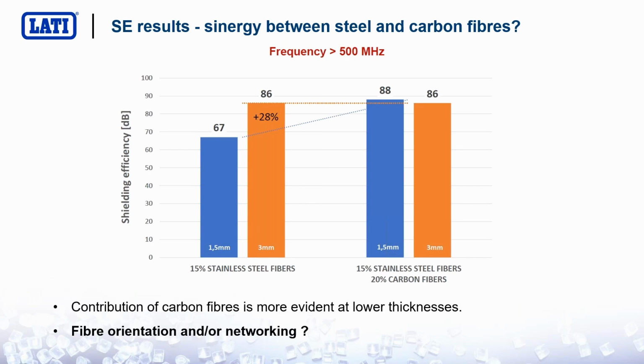We think that orientation improves networking, improves the number of contacts between conductive particles, and both shielding efficiency and shield response benefit quite a lot by adding carbon to steel. That's the reason why we are now developing a full range of compounds, featuring various concentrations of steel and carbon fiber, to propose a new family of EMI shielding properties.